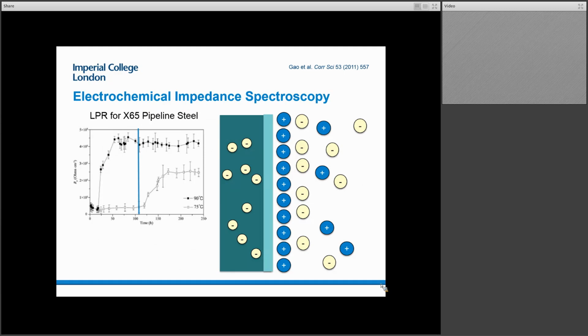So same sort of process of thought. And so they hypothesized that in that initial period, they do have some sort of layer on their substrate. And so I've highlighted that in light green to sort of illustrate it. And then by the end of the experiment, they don't know what they have, but they know they have more. They know they have an increased resistance, and so that could come from a thickening of the layer. It could come from the formation of a new layer, and in fact, the formation of the new layer could be quite interesting because it might in fact be a multitude of layers, and so on and so forth. But finally, it could also just be entirely new species. So this poses three hypotheses, but it poses a significant challenge.